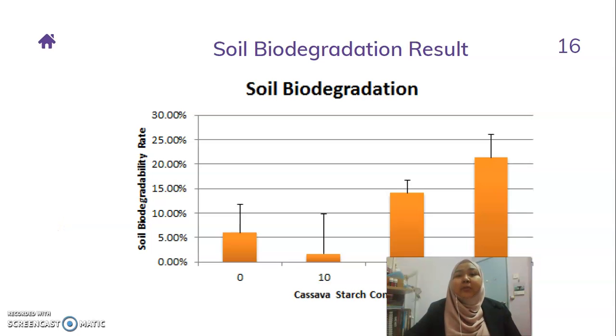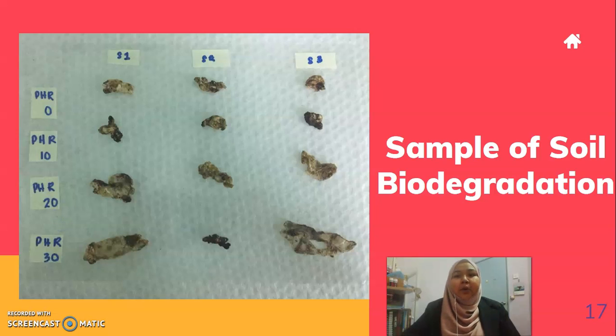Okay. The last one is the soil biodegradation result. As you can see, the highest value of soil biodegradation is at 30 phr. As I mentioned before, the starch helps the rubber degrade faster than usual. Okay, this is my sample of soil biodegradation after drying. My samples were buried in soil in a poly bag for 2 weeks and taken out. I wash them with distilled water and dry in the oven for 1 hour at 100 degrees C. Then I wait to get the final weight.